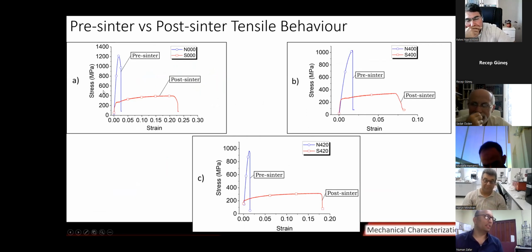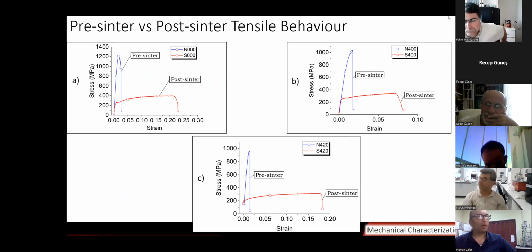This is the comparison between the pre-sinter and post-sinter wires. An overwhelming and dramatic decrease in the tensile strength, but at the same time increased ductility. It is safe to say that the sheath of the wires had very coarse grains because of the heat treatment. Although we have managed to acquire iron boride phases in the core, because of the sheath, the tensile behavior of the wire is such that recrystallized and coarse iron, coarse pearlite and ferrite grains have given a lot of ductility to the wires.